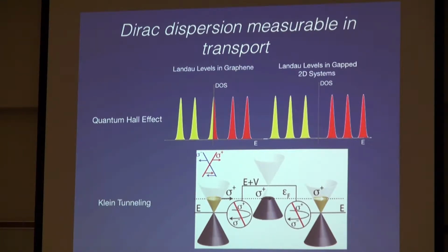The first place I'd like to point out where this existed was in the quantum Hall effect in graphene. You may know that in conventional two-dimensional electron systems, the density of states looks like harmonic oscillator states. But in graphene, the situation is different. Because of particle-hole symmetry and because there's a zero energy state at B equals 0, there's a zero energy Landau level that exists even when you apply a magnetic field. And this zero energy Landau level causes the values of the plateaus that you measure in the quantum Hall effect in graphene to be different.